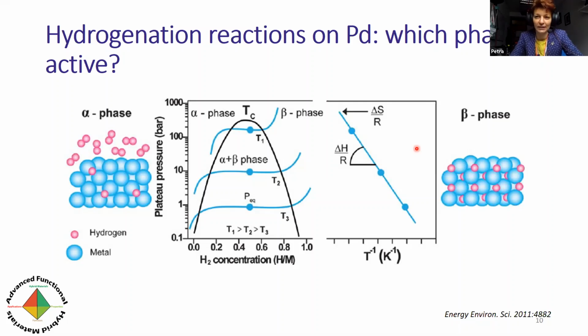And the reaction I will be talking about is a hydrogenation reaction. This is not the only type of reactions we're looking at, but in my view, this represents quite nicely the advantage of this kind of materials that we can have. And so here what we will be looking at is the combination of palladium. So what we would want is really to take a pore space to embed a palladium particle and use this composite as the catalyst itself. Now, why palladium? Palladium is known to be a quite good catalyst for hydrogenation reactions.